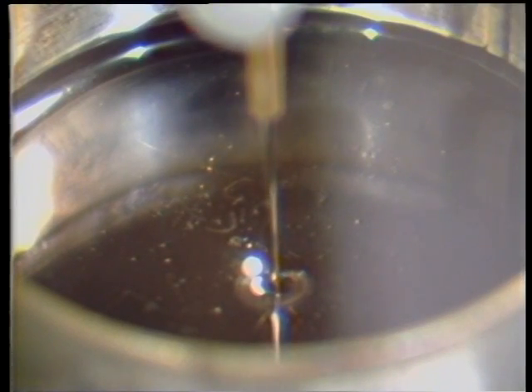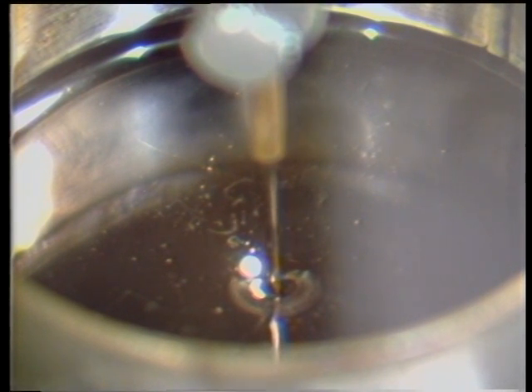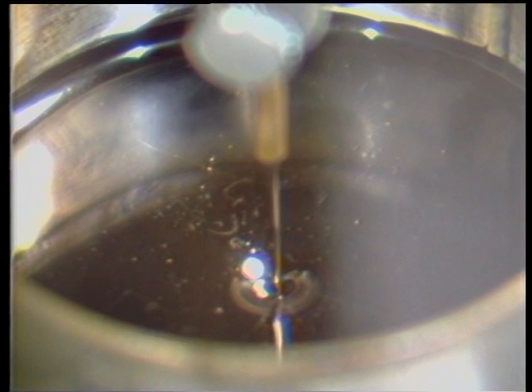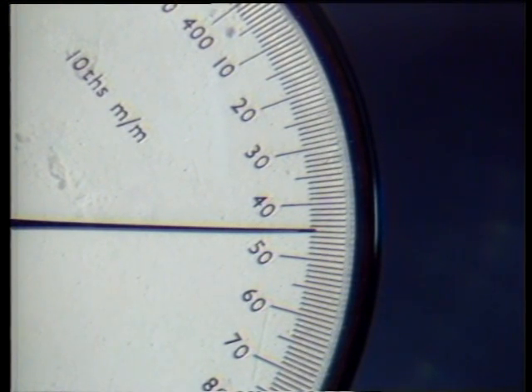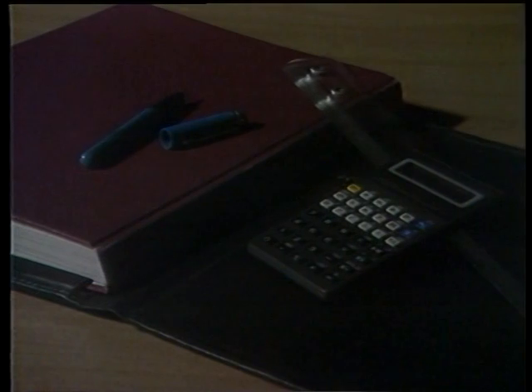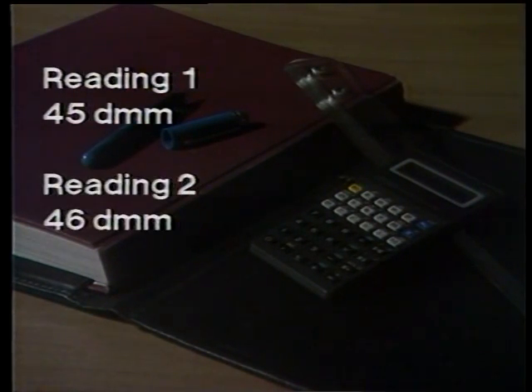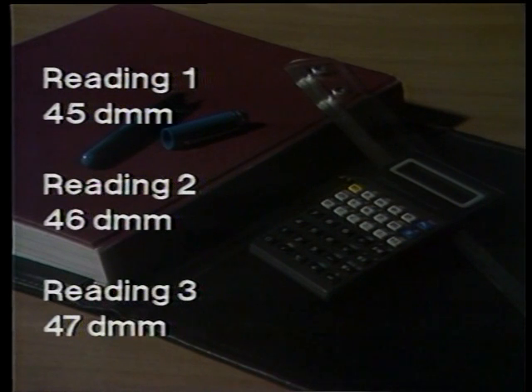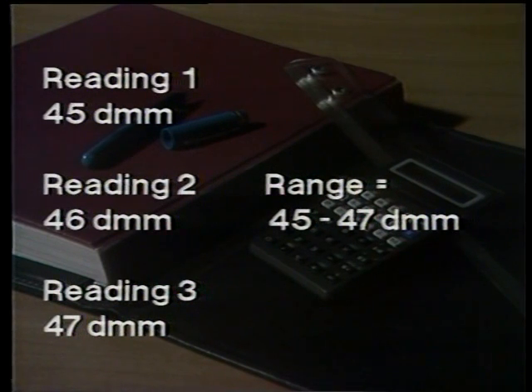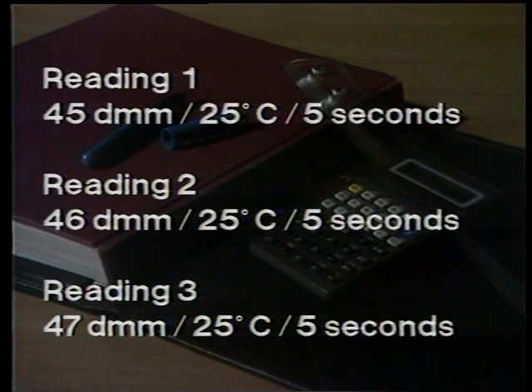Start the timer, which immediately releases the needle holder and allows the needle to penetrate the bitumen for exactly 5 seconds. Note the reading in tenths of a millimeter. Repeat the test to obtain 3 readings. The range of the 3 readings must not exceed the values given in the method. If acceptable, report the results in tenths of a millimeter and the test conditions.